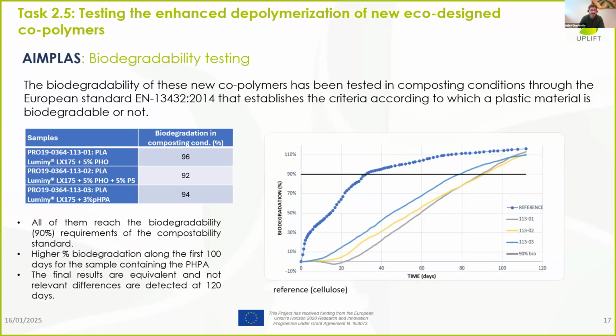As defined by the standardization protocol, we need to define the biodegradability, in terms of compostability, of our eco-designed polymers. Therefore, in this sense, the group from AIMPLAS stepped in and performed the standard test for the biodegradation process. In this case, we can see that all the samples reached 90% of the degradation or compostability compared to the standard reference, which was cellulose. And everything was detecting almost 100% weight loss within 120 days, which means that our samples not only can be enzymatically degraded, but are also compostable.